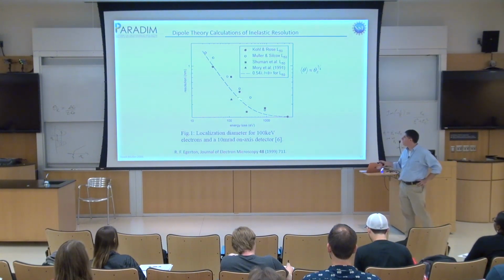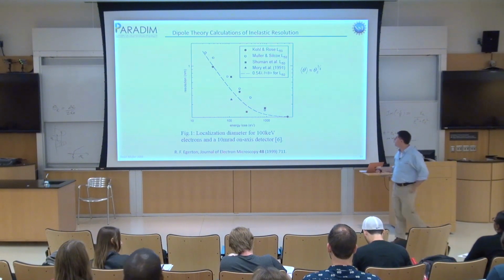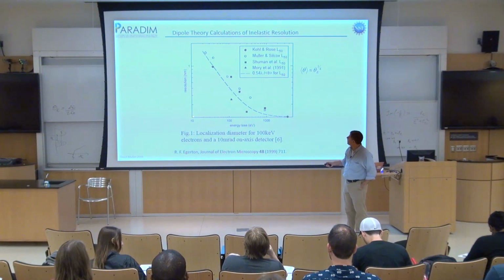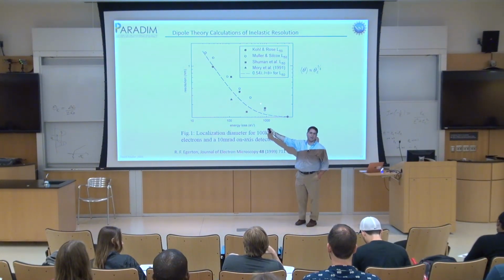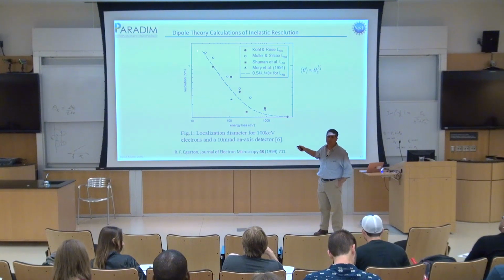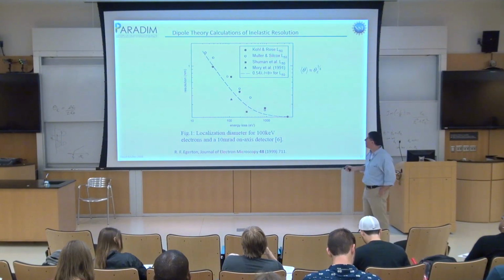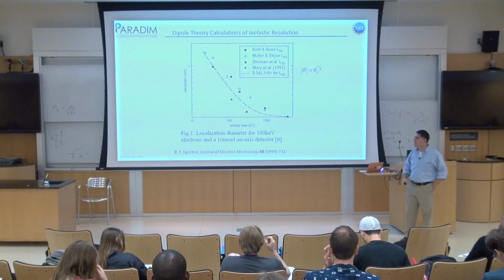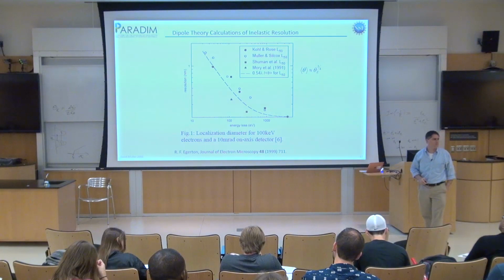The 80% radius is telling you basically how far out your tails go. What you'll see is that for core loss EELS, the tails go out to 0.1, that's 1 angstrom, this is 2 angstroms. So when I'm at a couple of 100-volt energy losses, my tails are quite localized, and it's easy to interpret the EELS. But when I go below 100 volts, look how my tails are shooting up. Now I'm up, this is a nanometer, that's 2 nanometers, that's 3 nanometers. This is a warning that funny things are going to happen in this energy range. And I'm going to talk about phonons at the end. Well, when I pick phonons, I keep extrapolating that curve, and then I get in real trouble.